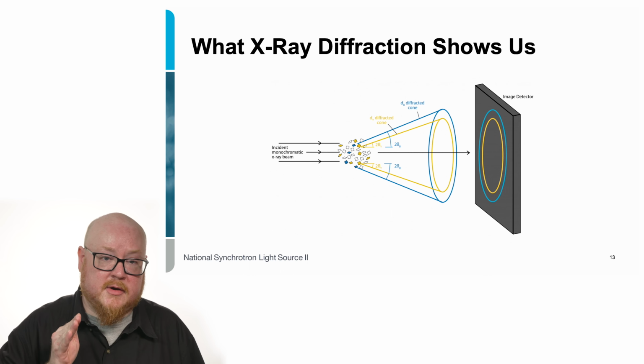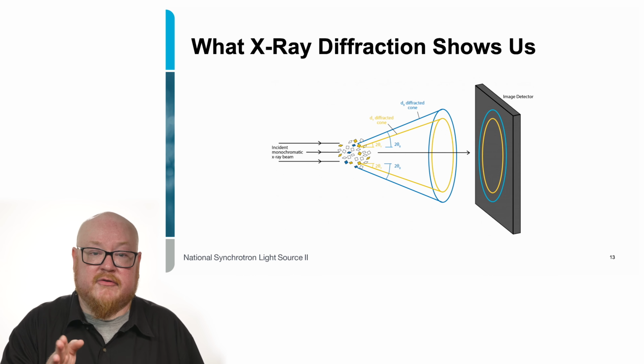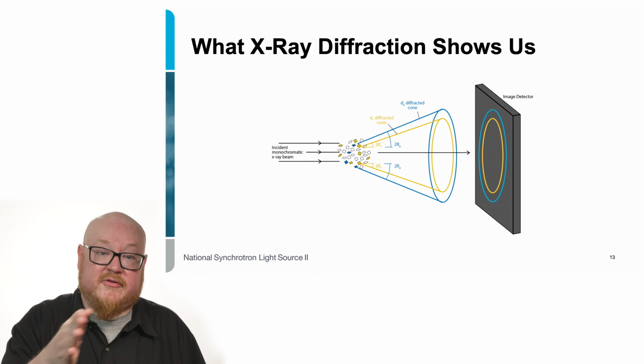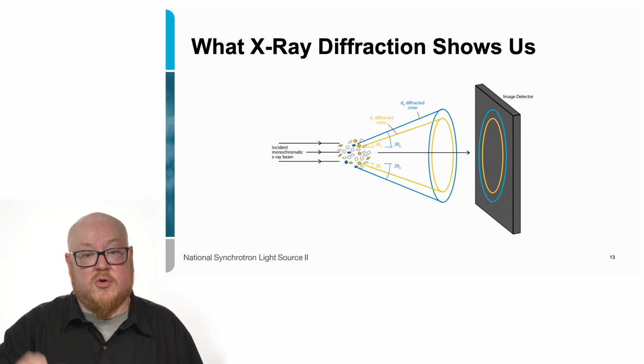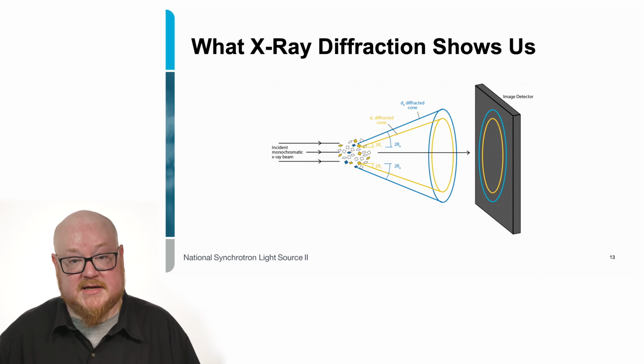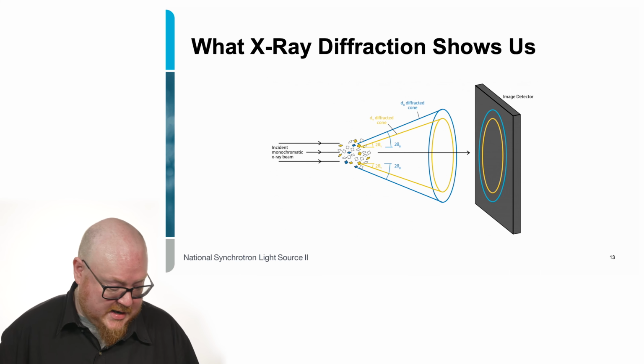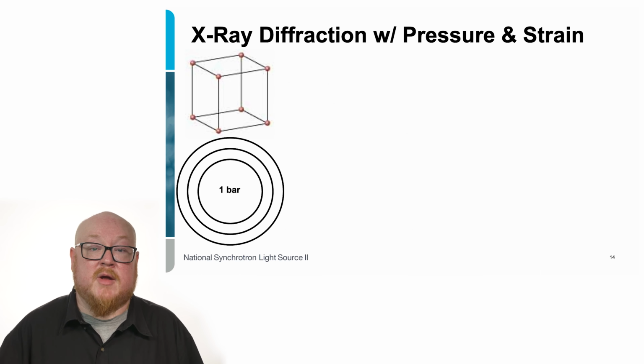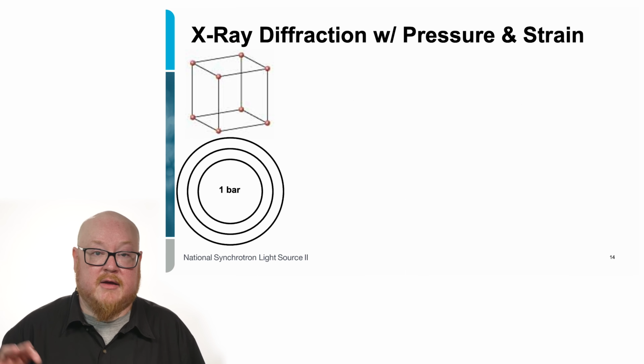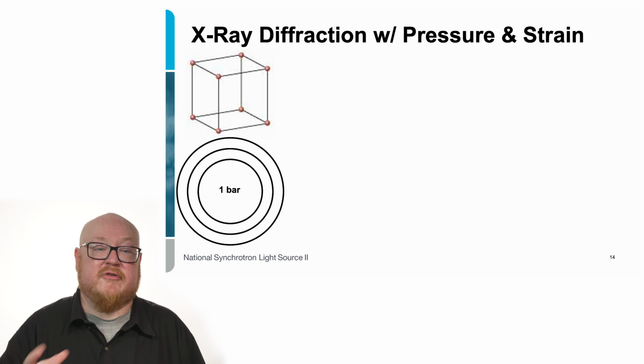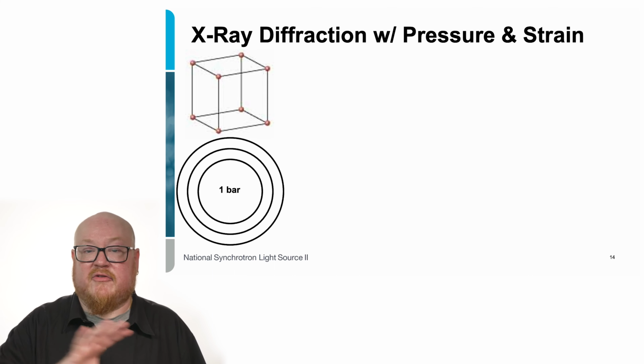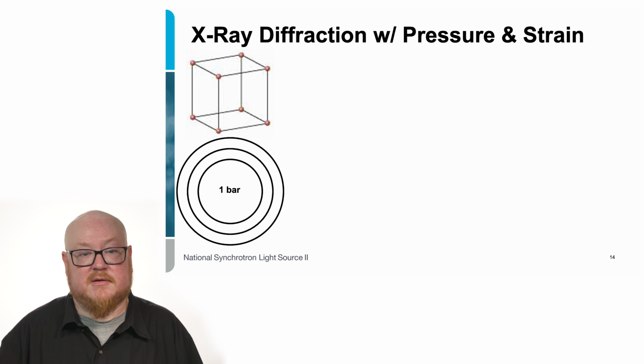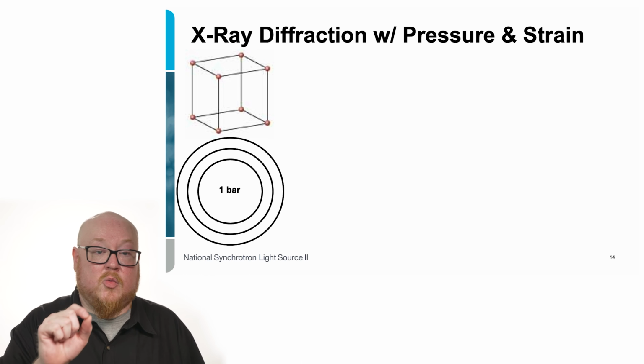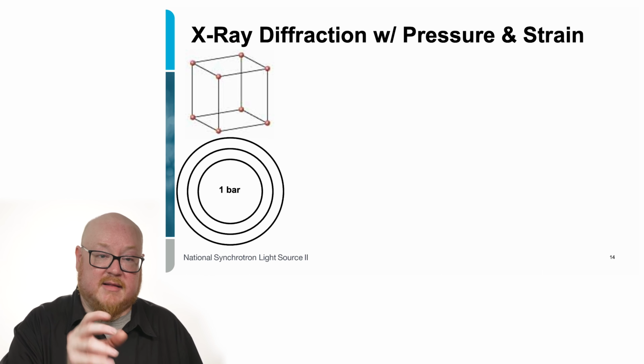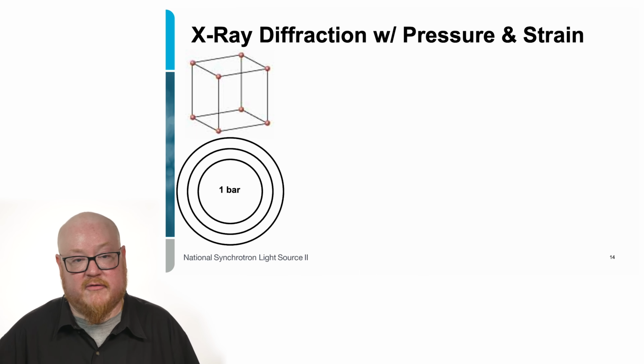When the X-ray beam goes in, it hits all of the different crystals, and the X-rays are scattered in these cone shapes that are then collected on the image detector to the right. And we can actually see some of the data in a moment. But what you're going to be looking for in these experiments in particular is, just as we talked about before, when we have a sample at ambient conditions, room pressure, room temperature, and 1 bar, we stick it into the press, we collect the X-ray diffraction, and we see rings that look very similar to the ones shown in this diagram here.